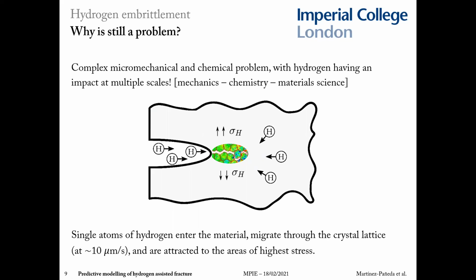We do know some things, of course. We do know that hydrogen atoms enter the material, diffuse through the crystal lattice relatively fast, and are attracted to areas of high hydrostatic stress or high volumetric strains, where the lattice expands and there's more space for the hydrogen to accumulate. But then in that fracture process zone, hydrogen interacts with materials in many different ways and at multiple scales.